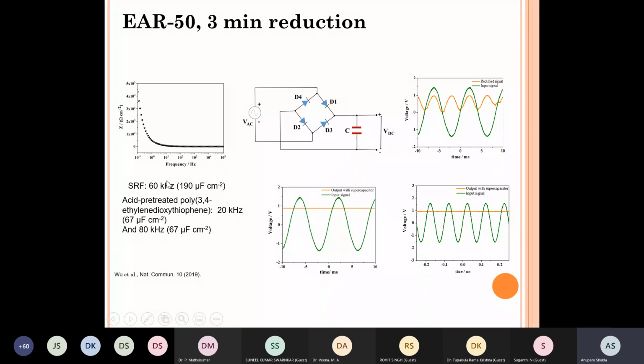For our capacitor, the SRF was 60 kilohertz. So therefore, we could even filter the signal at 50 kilohertz. So at 60 kilohertz, our areal capacitance was 190 microfarads per centimeter square, which compares very well with the best values reported in literature.